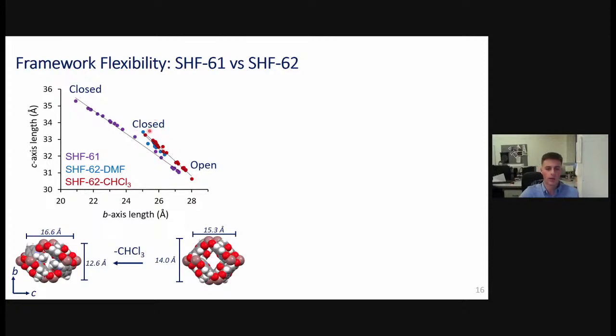And in another contrast to SHF-61, our original parent framework, we see that you can access the most closed pore form of the structure from either chloroform or DMF. So we no longer see that solvent dependency that we once had.